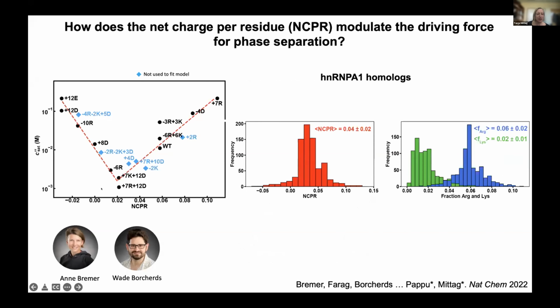I also want to mention that the minimum of this plot here is not at 0, but at small positive values, which made it difficult to see these relationships in the data. And we really had to go through this analysis to see this. And in addition, the net charge per residue of the natural sequences also peaks at around that same value. And of course, we see a preference of arginines over lysines in prion-like low complexity domains, suggesting that the ability to undergo phase separation may very well be encoded in these sequences.